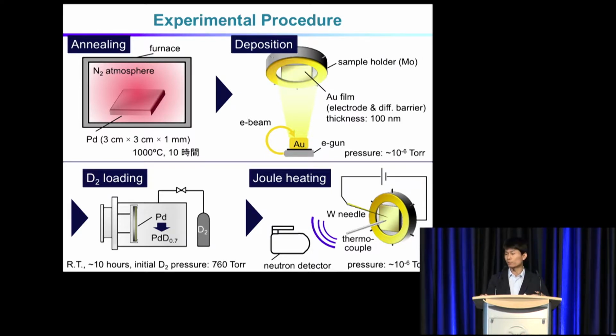This is the setup and procedure of our experiment. First, we anneal the palladium sample at around 1,000 degrees to make a monocrystalline phase as well as to clean the surface, because we found that with insufficient pre-treatment, we cannot obtain good or reproducible absorption of deuterium. And we deposit gold film on one side of the palladium plate as an electrode as well as a diffusion barrier, as I mentioned in the previous slide.